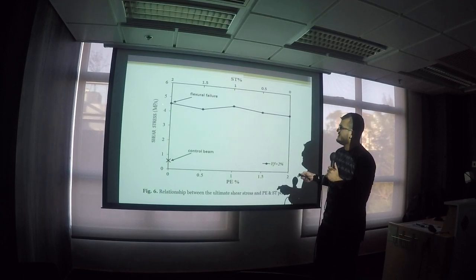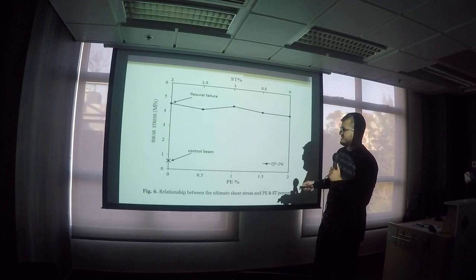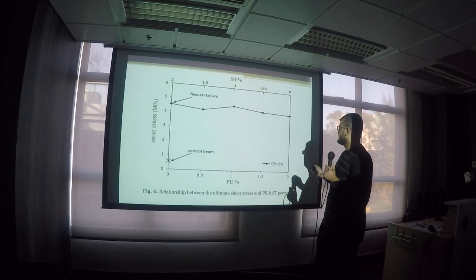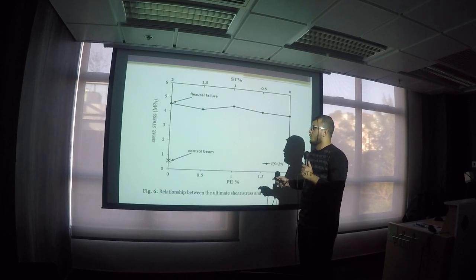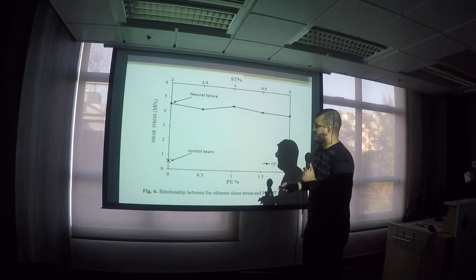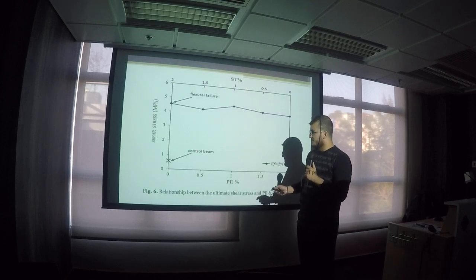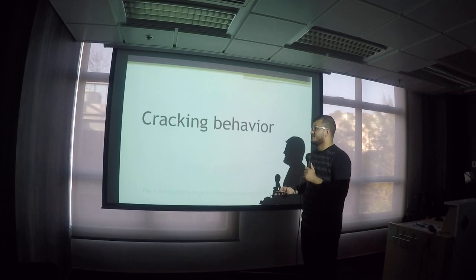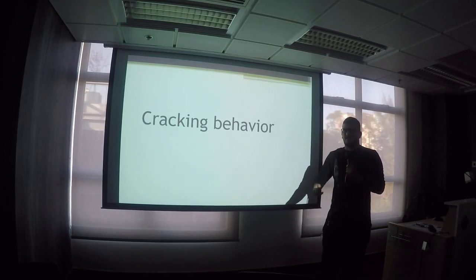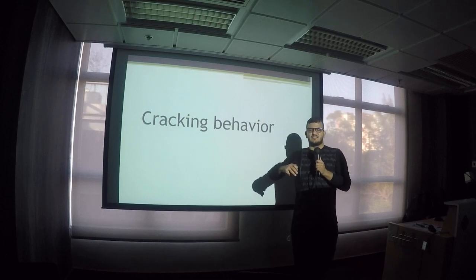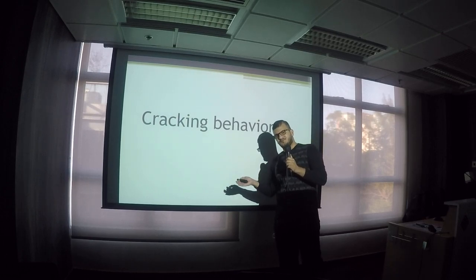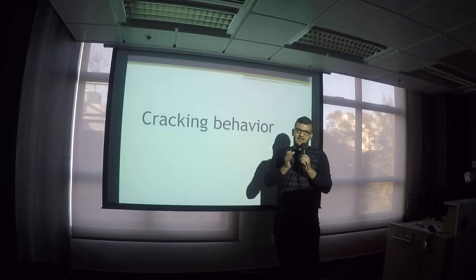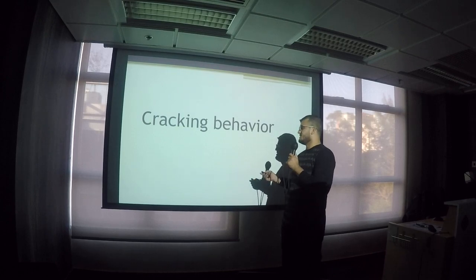However, this beam here, which was 2% steel and 0 PE, failed in flexure, while the others failed in shear. So this value should be equal to or larger than this one. However, if you compare it to the control beam, you can see here that it has been increased more than 8 times. Now, let's look at the cracking behavior, because the ECC material had multiple cracking behavior with bilinear strain hardening behavior.